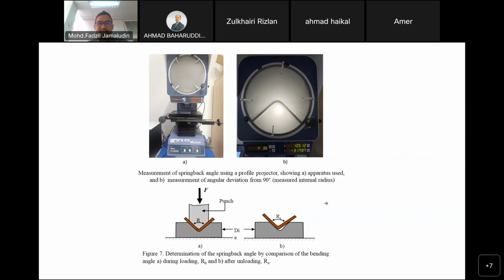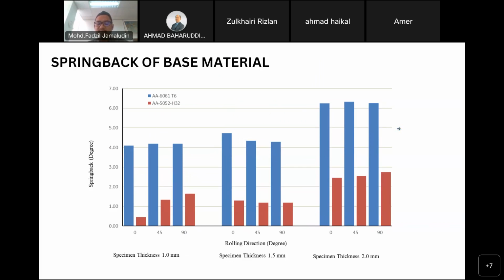We use a profile projector to accurately measure the spring back of the specimen after being punched. To compare, we tested the parent materials, so that we know the range of spring back for the aluminium 6061 and the 5052. From this evaluation, you can see that the spring back for 6061 is higher than the 5 series in our case, for all thicknesses: 1.0, 1.5, and 2 mm. We have some 2 mm also, just for comparison.